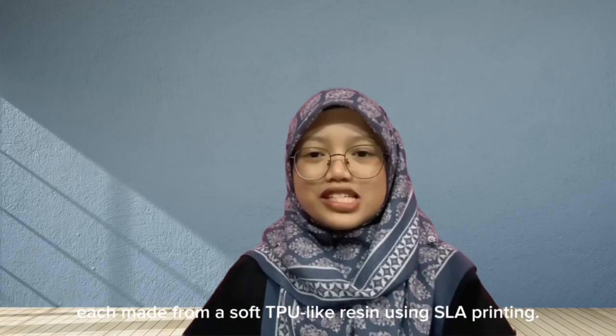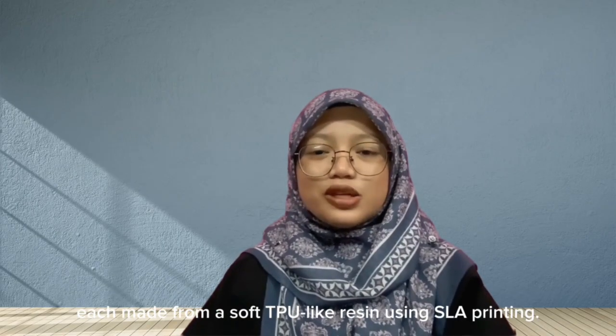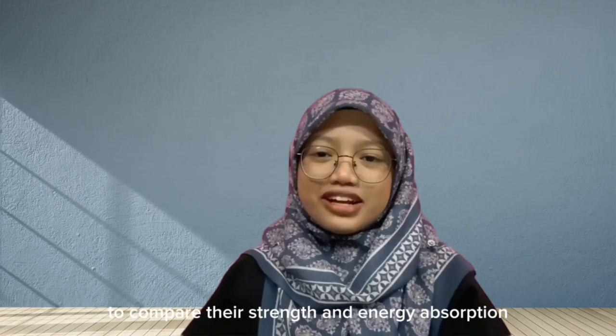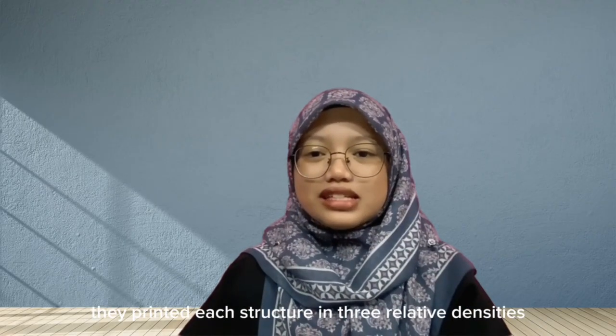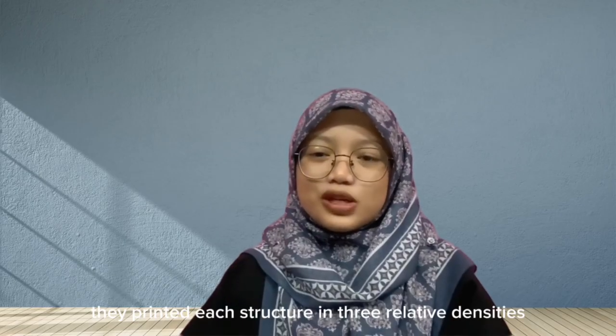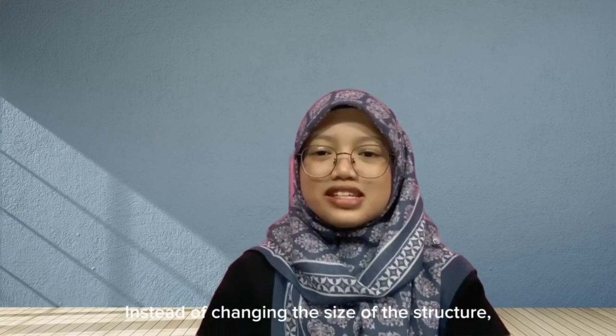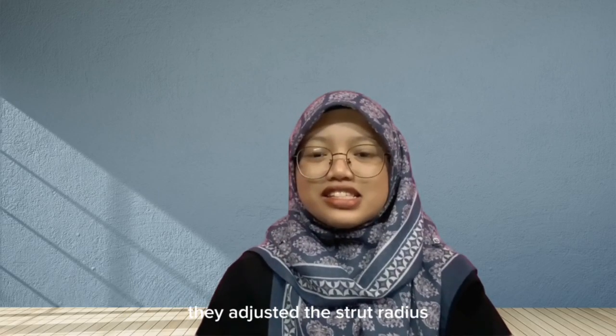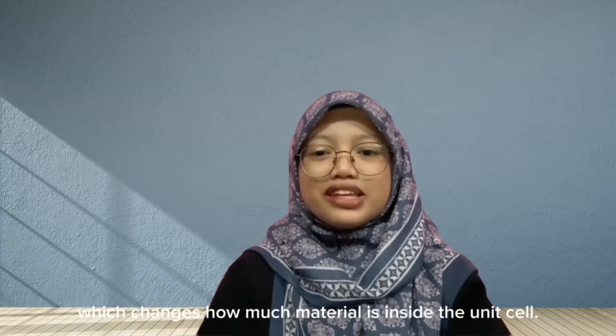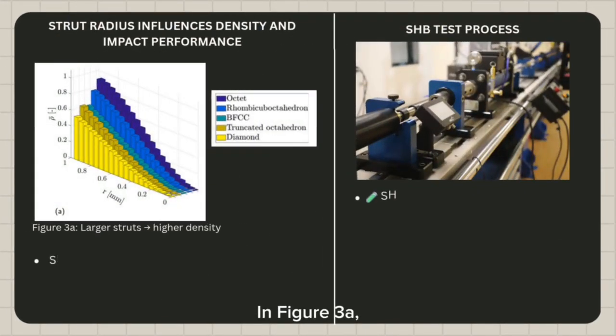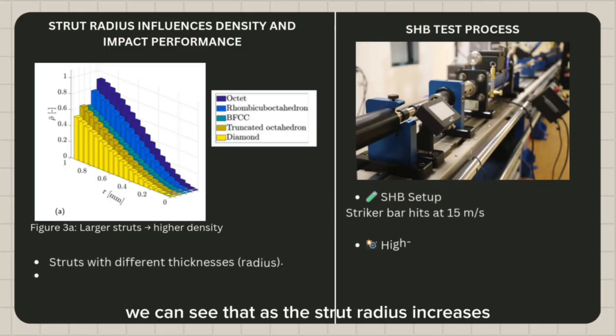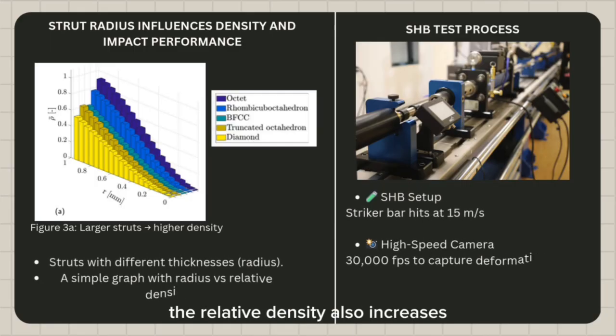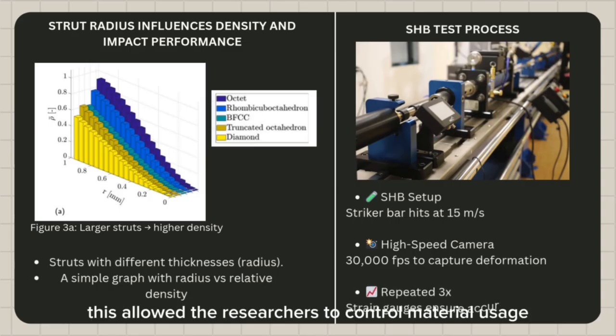The researchers tested 5 different 3D printed lattice designs, each made from a soft TPU-like resin using SLA printing. To compare their strength and energy absorption, they printed each structure in 3 relative densities, which is 0.2, 0.3, and 0.4. Instead of changing the size of the structure, they adjusted the strut radius, which changes how much material is inside the unit cell. In figure 3a, we can see that as the strut radius increases, the relative density also increases. This allowed the researchers to control material usage while keeping the overall shape the same.